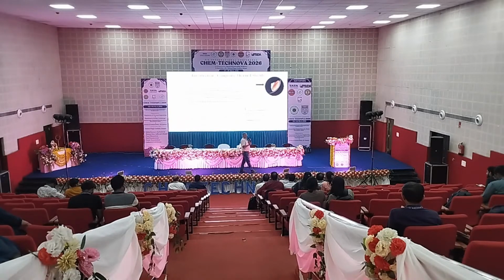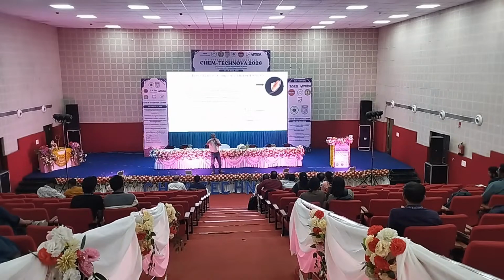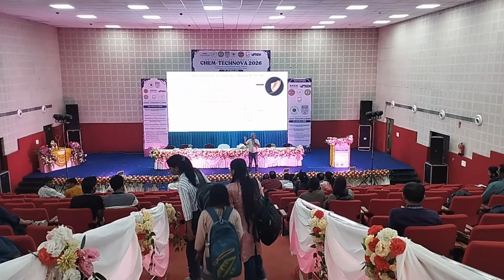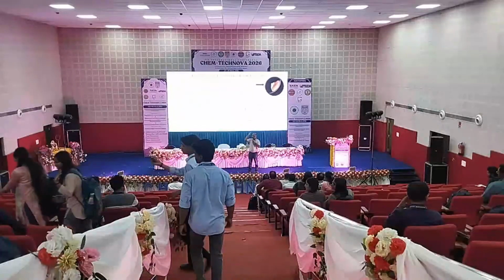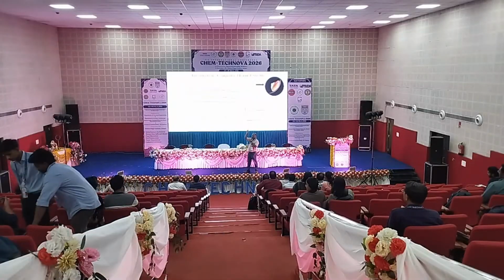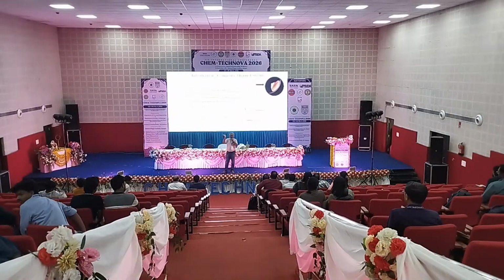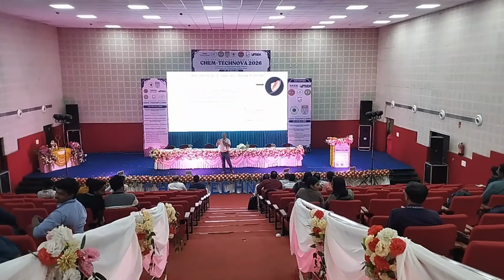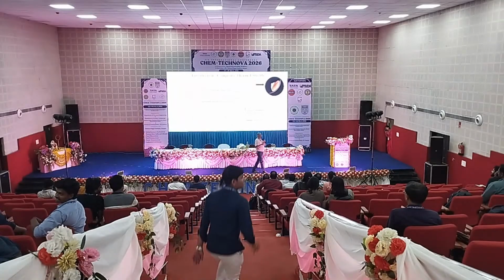Another very important parameter: what is the temperature range over which the parameters have to be studied? I cannot take thermal conductivity at room temperature, because the application temperature is 1200 to 3200 minimum. Can we have any equipment to measure thermal conductivity from 1200 degrees to 3200 degrees centigrade? It's very difficult. What should the equipment be made of? That equipment would have to withstand 3200 degrees centigrade. If I were able to make a material that can withstand that, I could straightaway use it in the space vehicle itself. So there are a lot of practical problems.